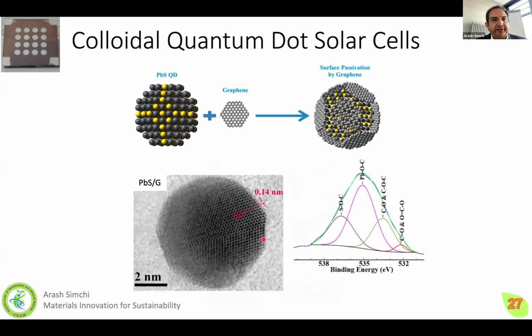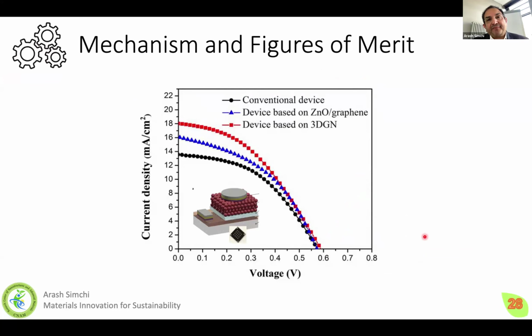I would like to share with you a TEM image of our quantum dots. You see this honeycomb structure of the graphene on the surface. And also the XPS shows that we have a hybridization between the PbS quantum dot and graphene. And then we measured and made a solar cell out of it. And you see that it is possible. It doesn't need to use a lot of organic materials. We can use carbon materials as a source of a sustainable system.